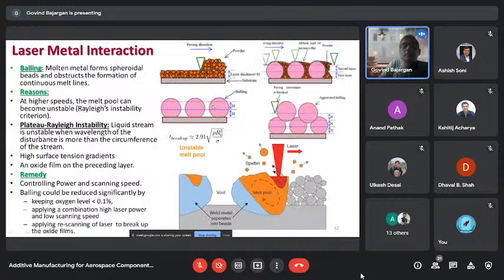Here I'm showing the balling effect. What happens when laser energy is very high and speed is high, the laser is moving in a line, so we are creating a liquid line, and this line becomes unstable. It's Rayleigh's stability criterion. It is similar to water falling from a tap: if we narrow things down, that continuous stream divides into small droplets. The same way it happens here. Rayleigh's instability comes into play, and instead of a single continuous track, we end up with a formation of balls or droplets, which will hinder the subsequent builds also.